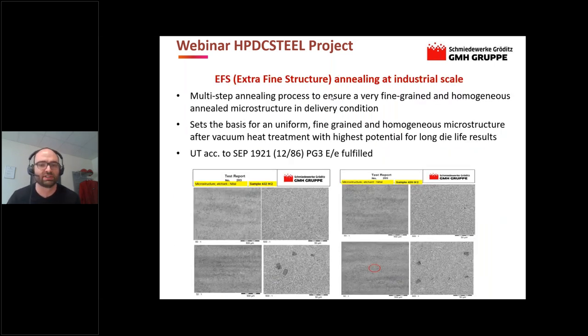Subsequent to the forging process, an annealing process followed. This is a special annealing process called EFS, extra fine structure annealing. This is a multi-step annealing process to ensure an annealed structure in delivery condition with a very fine grain and a homogeneous appearance. Additionally, the homogeneous annealing structure sets the basis for a later uniform and fine-grained microstructure in hardened and tempered condition after vacuum heat treatment of the later die. And at this point, the base is already set for a prolonged die lifetime.